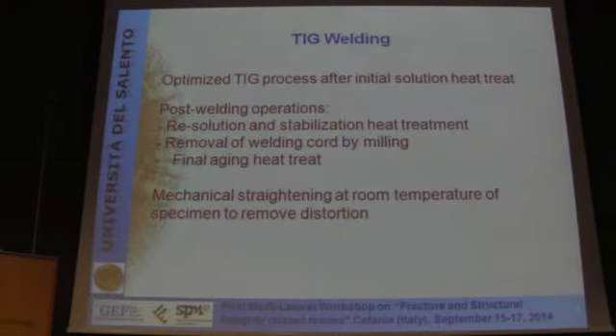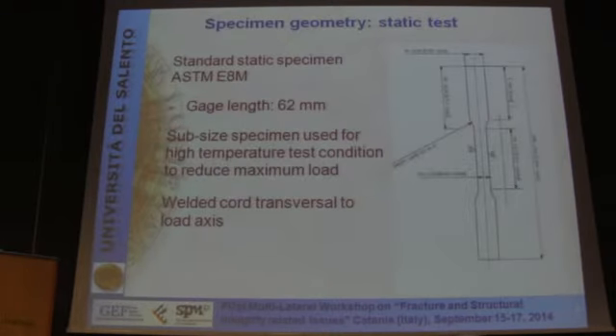We used this plate to obtain several welded plates. The material, initially age treated, was subjected to a solution treatment. After this, a TIG welding process was carried out, and after welding, we carried out a solution and stabilization heat treatment, the removal of the weld bead, and the final aging heat treatment. In some cases, it was necessary to carry out a mechanical straightening of the specimen to eliminate its distortion. These are some details about the geometry of the specimen.